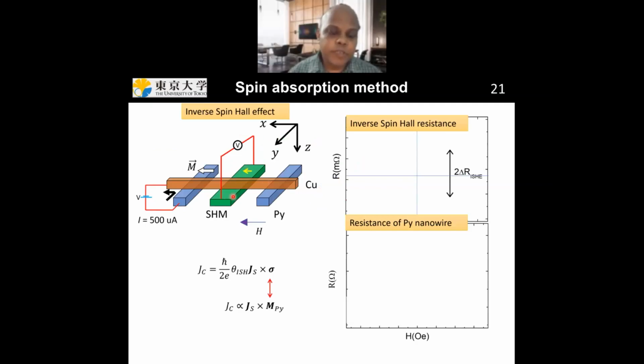So now after you have demonstrated the spin absorption, the next thing to do is that if you put a voltmeter, then obviously because some spin current got absorbed by the spin Hall material, it will produce a voltage due to the inverse spin Hall effect. But since we know that spin current, charge current and spin polarization directions are mutually orthogonal to each other, you will not detect voltage in all conditions. You will detect a voltage only when the spin polarization of the spin current is pointed along the x direction, as shown by this yellow arrow over here. And you can control the spin polarization direction by controlling the magnetization direction of this injector ferromagnetic electrode. So suppose you apply a large magnetic field along this x direction, you saturate the magnetization along this x direction, and you measure the voltage, then you will get a finite inverse spin Hall resistance over here.